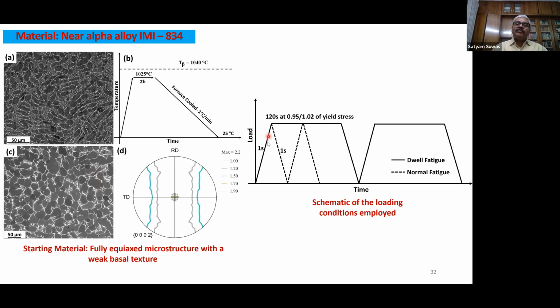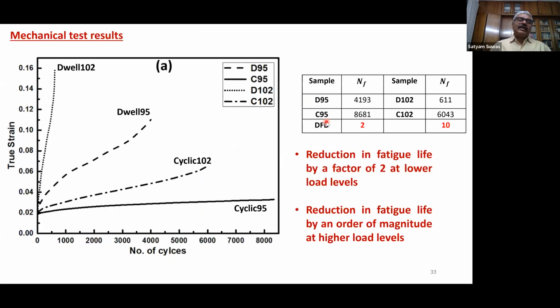And again, this sample was subjected to a similar type of cycle as in the previous condition. And then we have seen that this was the normal fatigue and this is for dwell fatigue. We tested it at two levels of yield stress. One was at 95% and one was slightly over the yield stress values. There is a reason for that, and that will come later. This is basically the test protocol for this alloy.